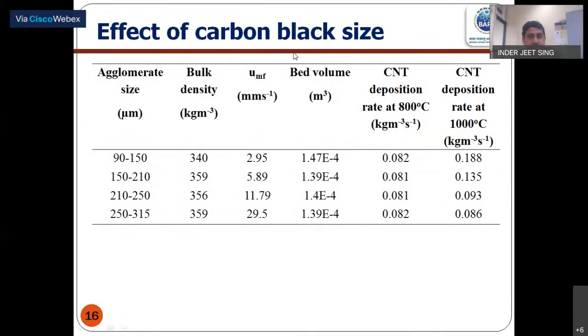Next, we varied the carbon black size. At low temperatures, after varying the carbon black size we are not seeing much effect, but at high temperature, at 1000 degrees, we are seeing the effect. If we remember the first Arrhenius plot, at the higher temperature there is an effect of diffusion, so that is coming here. So there is an effect of internal diffusion. Due to the change in the size of the carbon black, there is a deposition rate change.